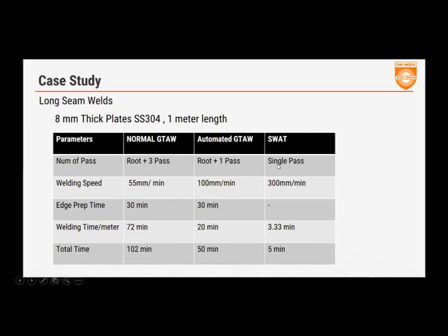In SWAT, with a single pass at a speed of about 300 millimeters a minute, no edge preparation required, maybe about 2 to 3 minutes of setup time, 3.33 minutes of weld time, you can complete the same job in 5 minutes. You can look at the jump in productivity you can expect, right?